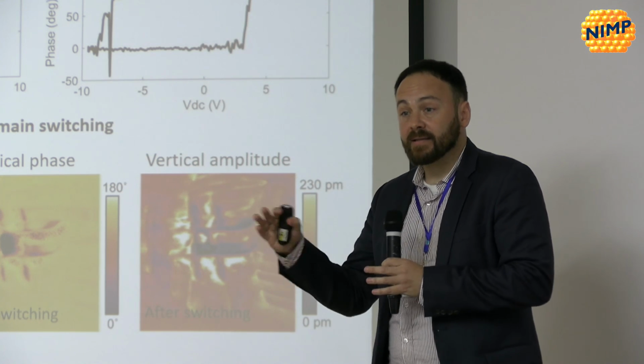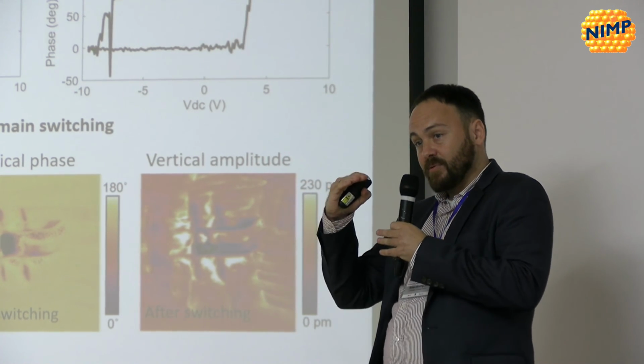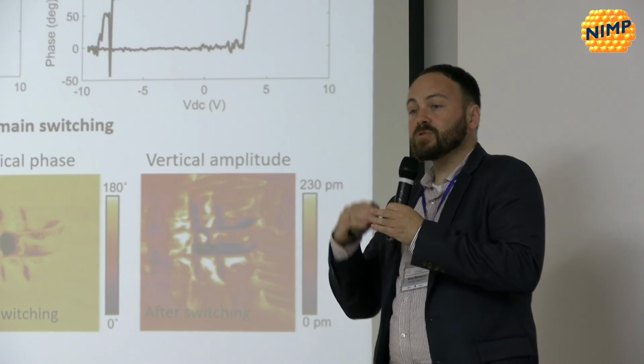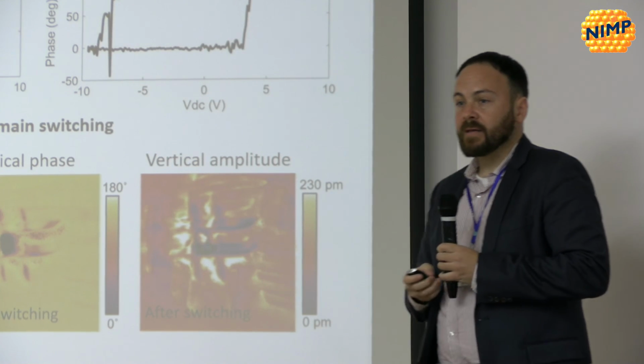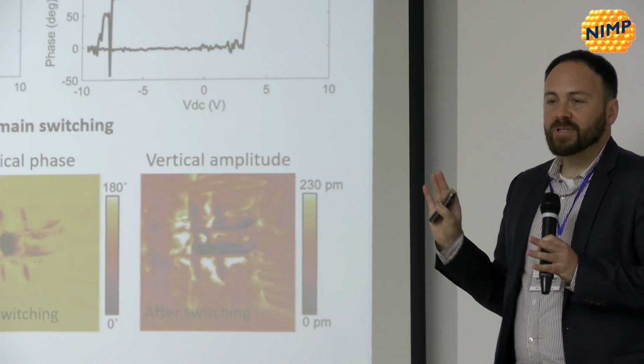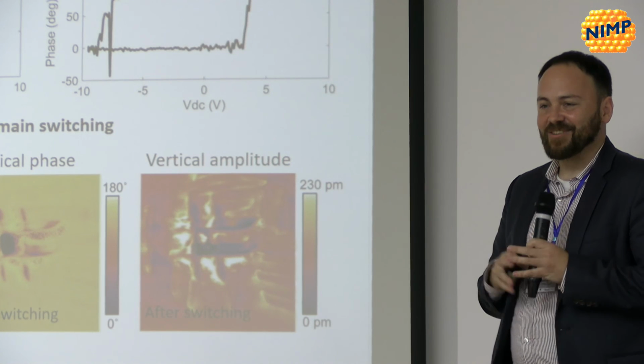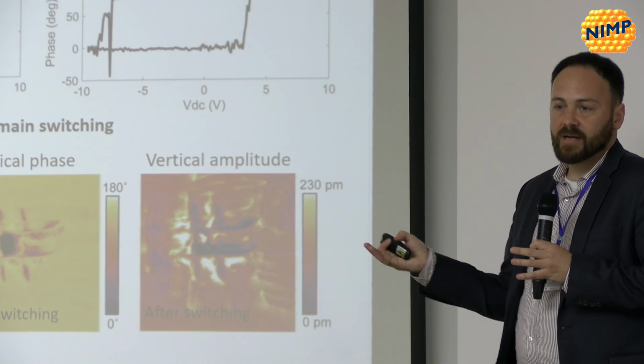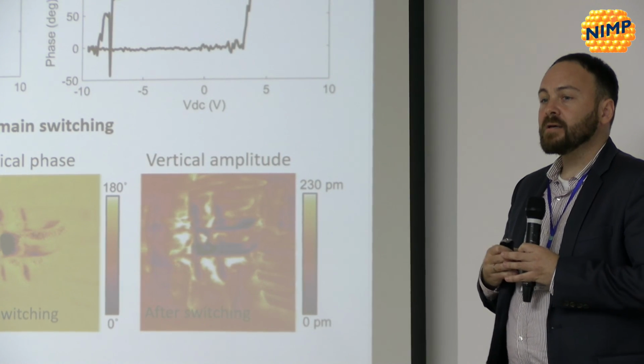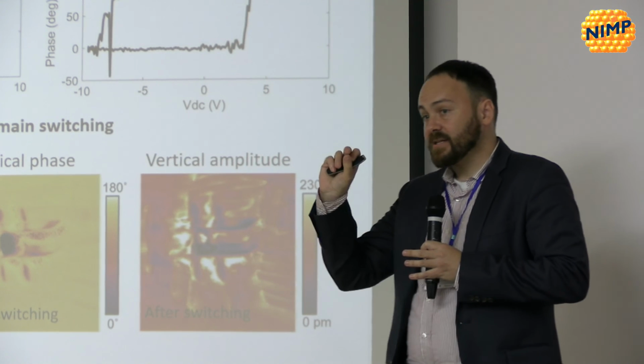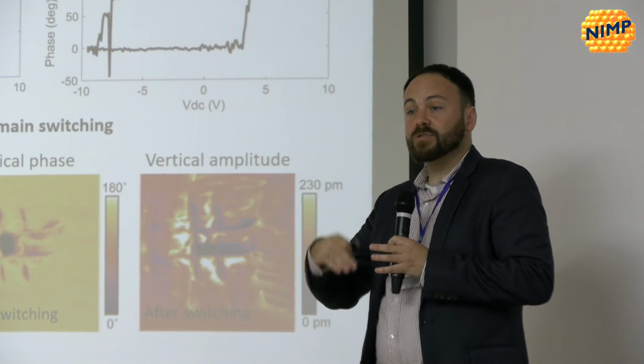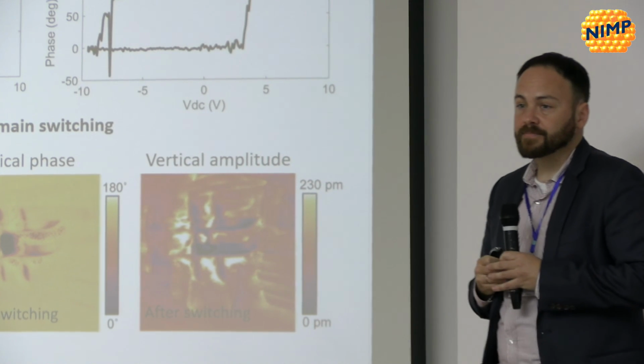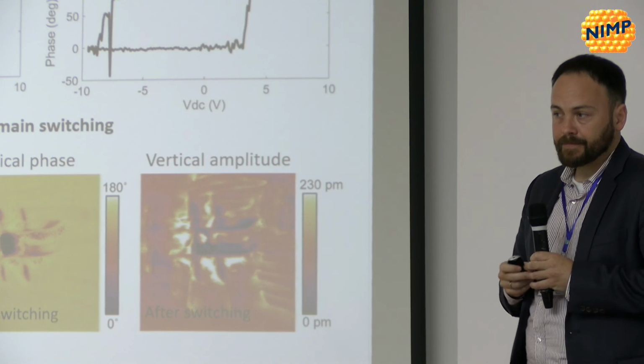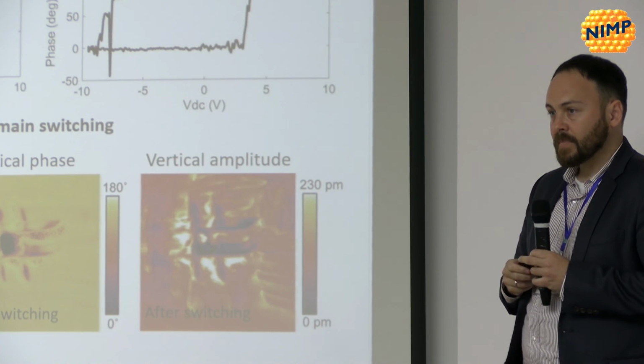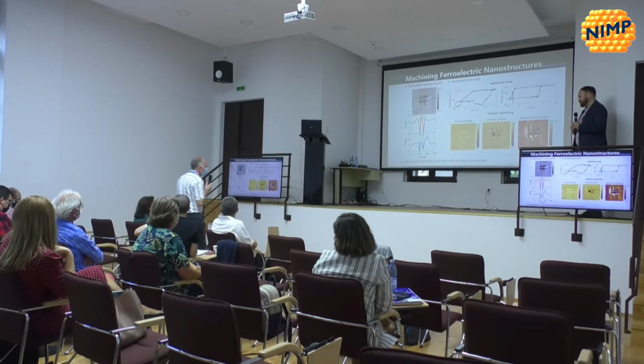So that goes along with the fact that we think we're squeezing the dead layer, because more of the voltage is then going to the ferroelectric. D33 is getting high, or just the resonance is higher? We're only looking at effective D33, yeah. Okay. So that's getting higher in our amplitude loops when we're doing the measurement. So it's consistent with the idea that we're squeezing the dead layer, and so more voltage is going across the ferroelectric.